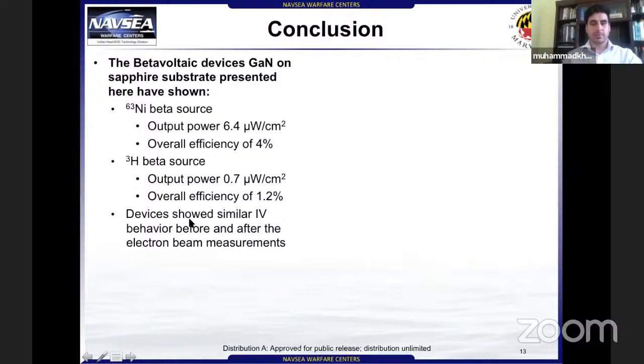One big concern with betavoltaics is that high energy beta particles can damage the atomic lattice structure of the semiconductor. So we did the dark IV after the EV measurements to see if there was any damage. We did not notice any damage. Our devices behave similarly before and after the EV measurements.